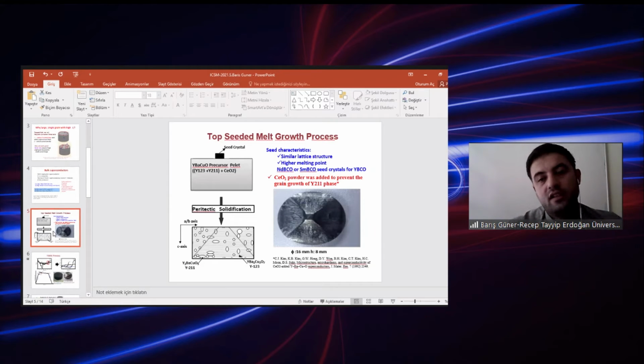I would like to say some things about the top-seeded melt growth process. Firstly, we choose the seed. The seed is a very important parameter for the top-seeded melt growth process, because the growth process starts by using the seed. The YBCO includes superconductive powder Y123 and non-superconductive powder Y211. Sometimes we use the green phase. So the seed characteristics are very important.